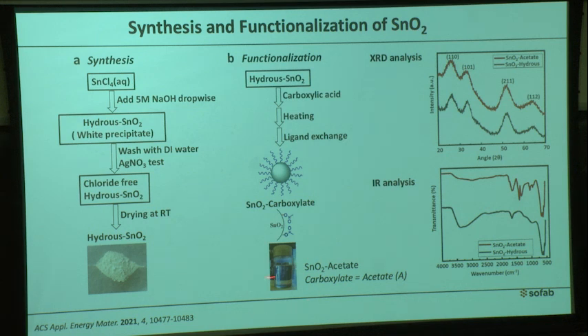But we still don't know if there is still tin oxide present. To identify this, we characterized the tin oxide using normal characterization techniques, XRD and IR. If you look at the XRD diffraction pattern, the peak positions of the tin oxide before and after functionalization - the solution tin oxide and the powder tin oxide - are aligned with each other. That's why we can say that after functionalization, this clear solution can still be in the tin oxide phase.